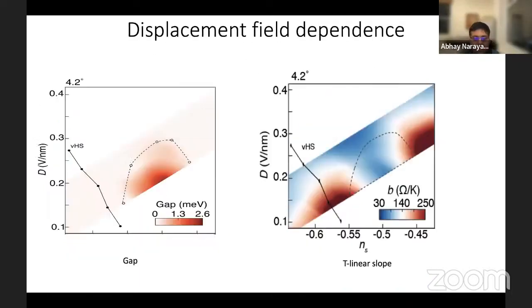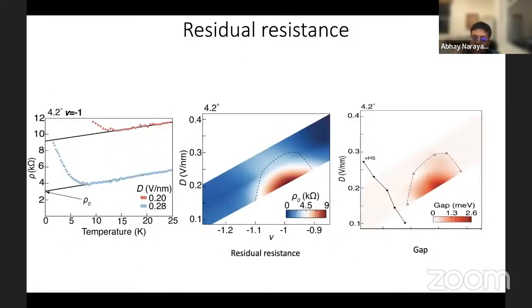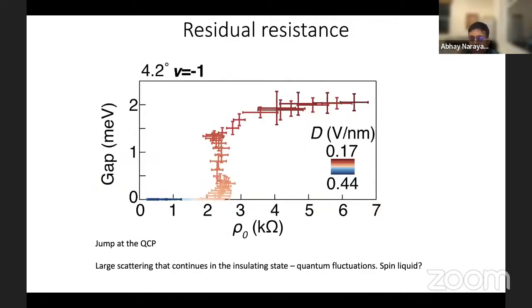So not so far, but I should say, we are still somewhat early in measurements, right? So one thing that is already, we know that there has to be a little bit more to the story. For example, we see that as a function of density, that the insulator survives to about 10% doping away from the half filling point. And theoretically, that would not be reasonable, right? So whether there's something else going on, there are other states on this boundary is yet to be determined. Let me say, the problem is that there are not that many measurements one can do on these systems. Yeah, so that's yet to be determined.